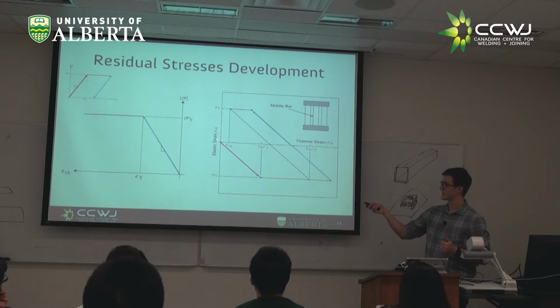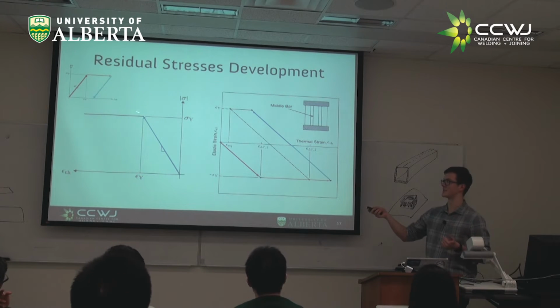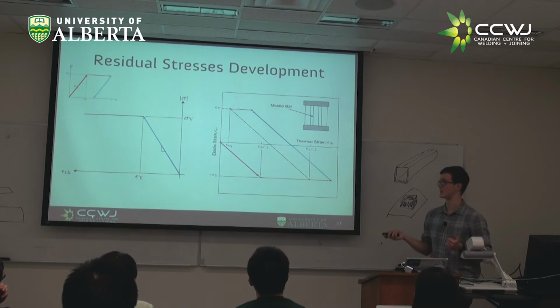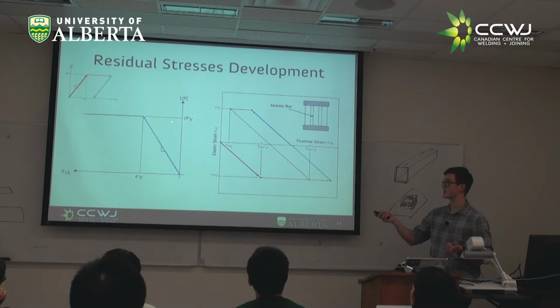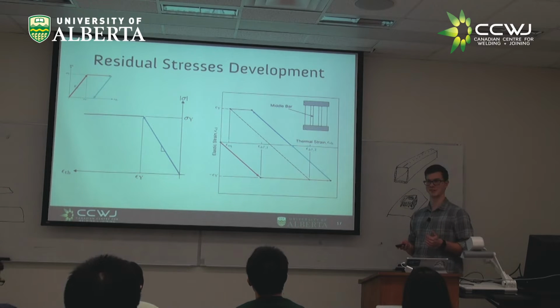In this case, what's happening is we started off in compression, we reached some peak temperatures, and then as we cooled, we end up crossing what was our zero strain curve. And typically in a diagram like this, you can't go beyond your zero stress. You're either doing a compressive test or a tensile test. So we have to start a new test where we look at it, not from our zero state, but from this reference state, where as we cool back, we're cooling back towards what our zero state was. So in reality, you could imagine this zero axis, if you wanted to deal with zero thermal strain, would be somewhere over here. Does that make sense to everyone? I'm starting to see some glazed eyes.